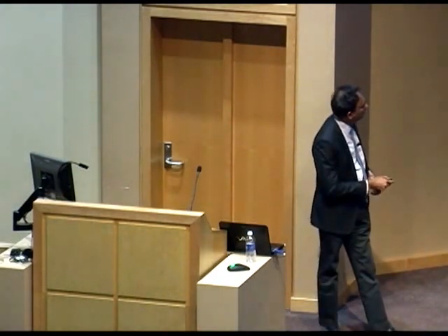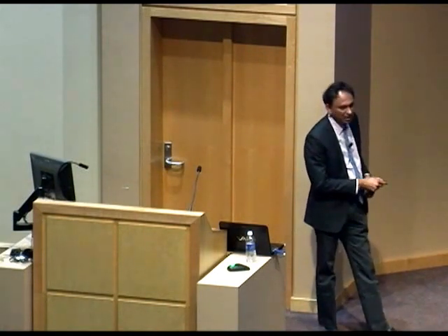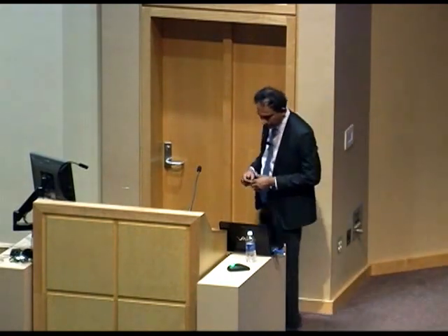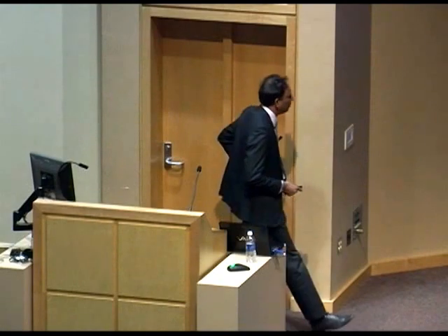One of the reasons why this happens is that if I start to build a BNC system using techniques like CVD, what happens is that instead of mixing and getting a uniform phase, I get segregated domains. Essentially, the boron nitrogen tends to come together and the carbon tends to remain separate. So what I end up with is this quilt or patchwork of boron nitride domains and carbon domains. And when we published this paper a couple of years ago, this was the first CVD growth of this kind of hybrid system with boron nitride and carbon. Essentially, we found that these domains are segregated, nanoscale segregation of these domains, and unless you have the right kind of window, you never get to this BCN kind of thermodynamic phases. But this allows us to do certain things.